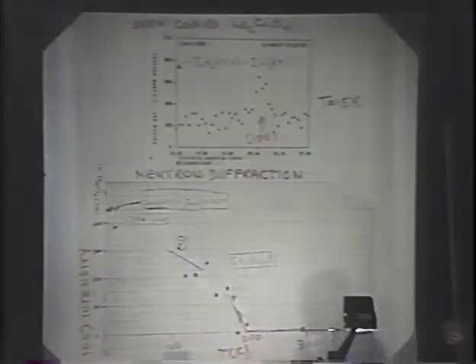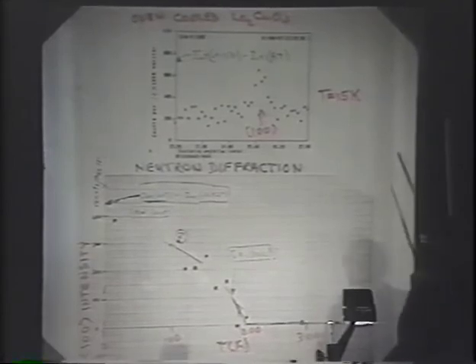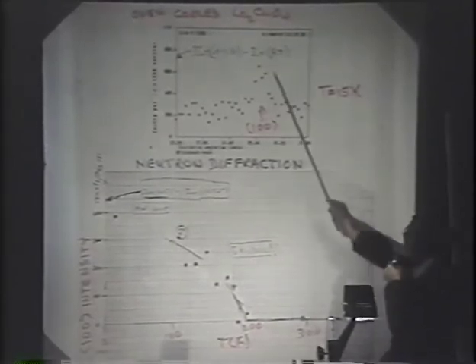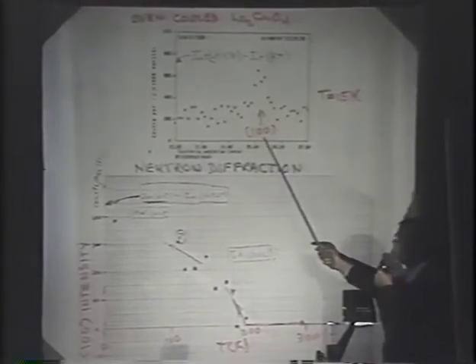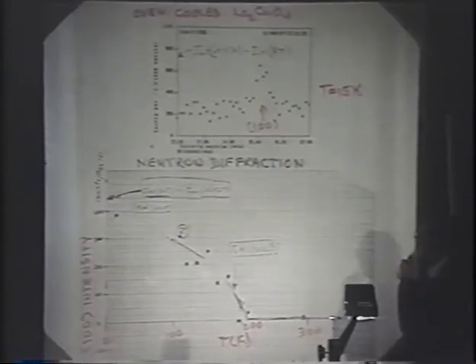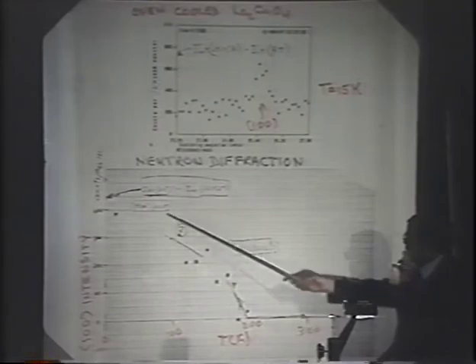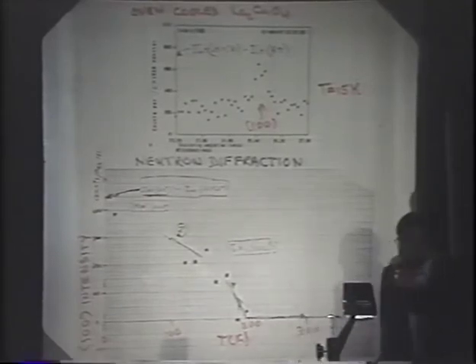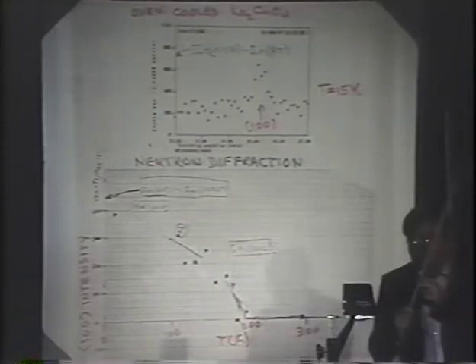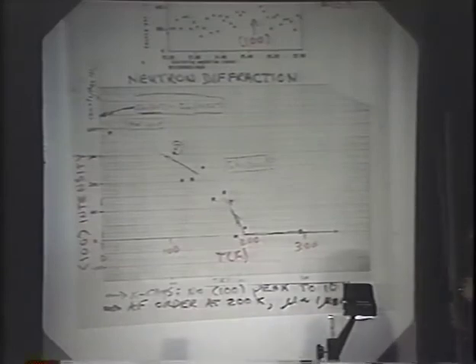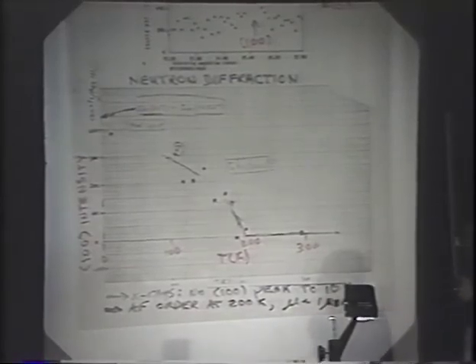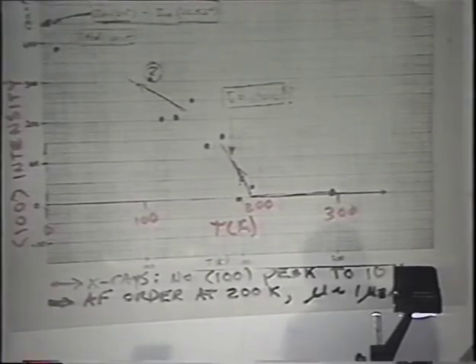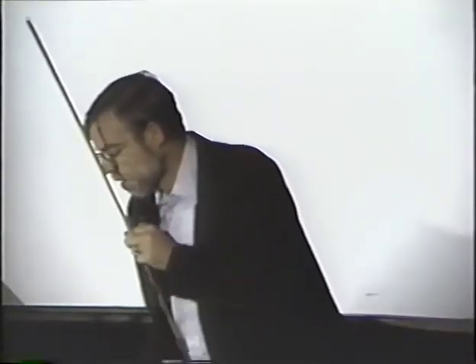Well, when you think you have magnetic order, you do neutron diffraction. So that's what this is. We cooled the La2CuO4 down to 15K, and a new peak occurred at the old crystallographic 100 position, and its intensity as a function of temperature is shown here. So the question is, what kind of transition is it? Is it crystallographic or magnetic? The X-rays show no 100 peak, so evidently it's antiferromagnetic. And from the intensity of the peak, the moment on the copper is about one Bohr magneton per copper.